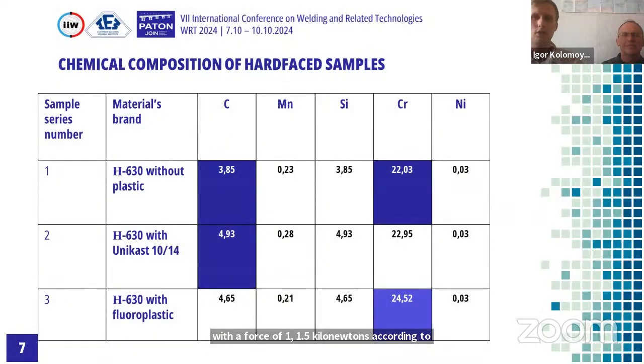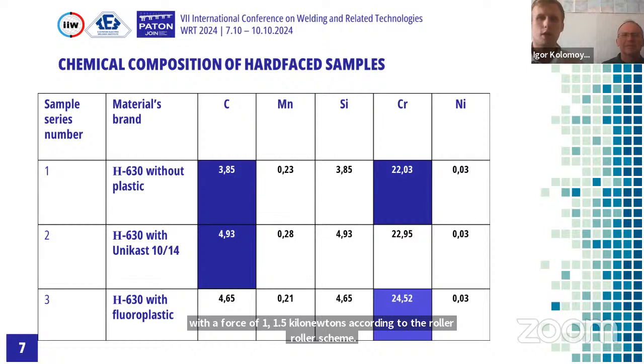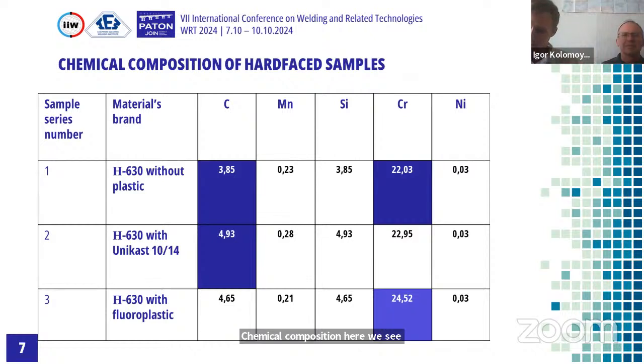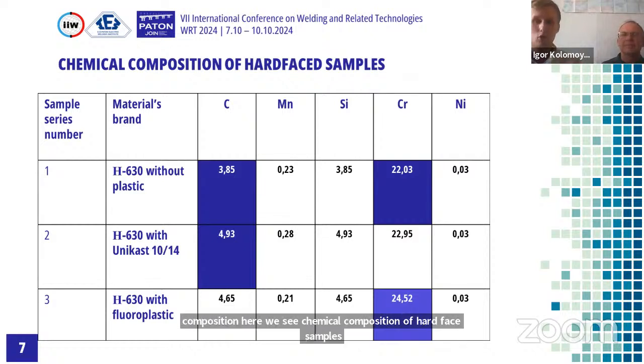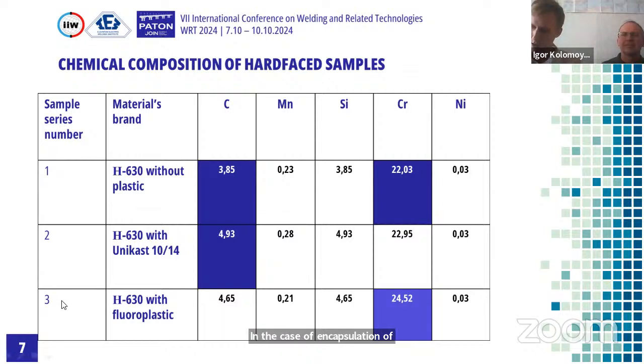Here we see the chemical composition of hard face samples. In the case of encapsulation of chromium carbide particles, samples 2 and 3, an increase of the presence of carbon in the deposited metal is recorded. Moreover, the use of polyurethane unicast caused a more significant jump in carbon values, and the use of fluoroplastic caused a significant increase of chromium values.